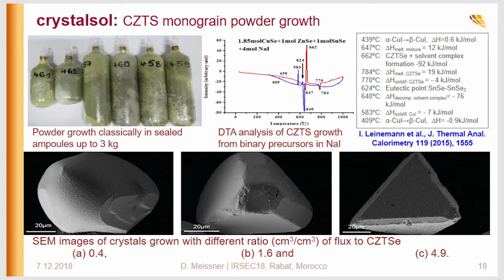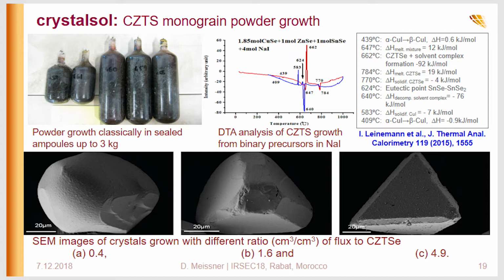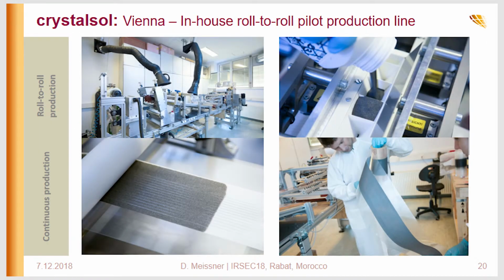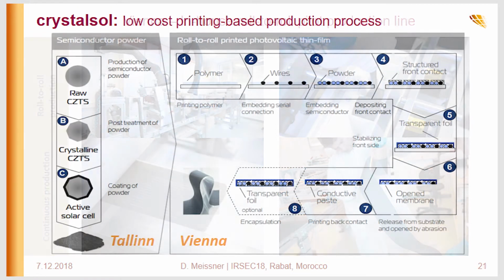You keep this ampoule at high temperature until the growth gives you the right size of your particles, and then you cool it down. It looks black, because the CZTS has formed. You just put this into water, the salt dissolves, and you have your powder. Very simple. And then you use the powder for printing. Yeah, you can print it endless, of course, the way we do this, actually.